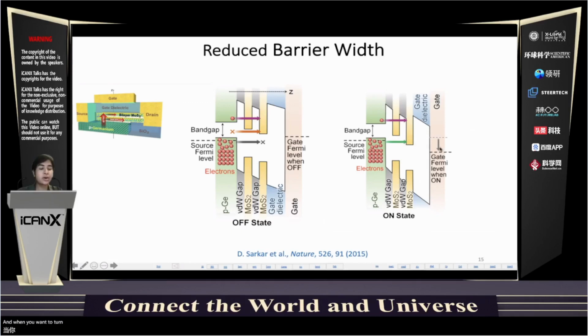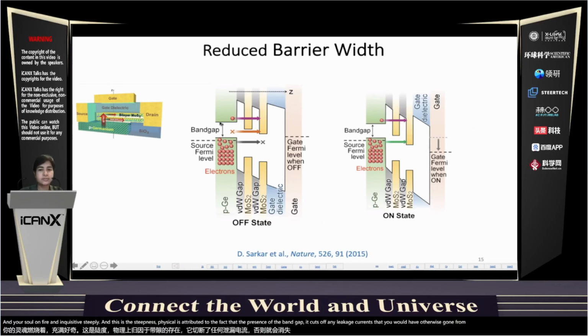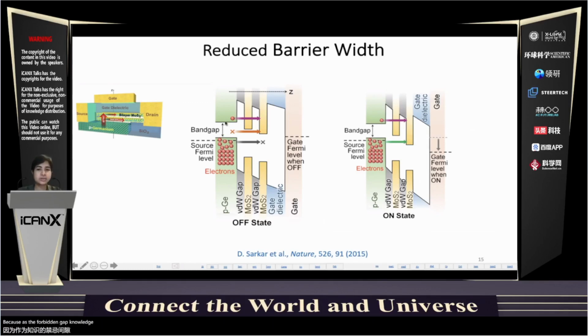And when you want to turn on the transistor, you apply a voltage to the gate, and you bring all the bands down. In that case, the filled regions in germanium actually coincide with the empty regions in molybdenum disulfide. So a lot of electrons can flow from the 3D source to the 2D channel, and so current increases steeply. This steepness is attributed to the fact that the presence of the band gap cuts off any leakage current that you would otherwise have got from this region, because it's the forbidden gap and no electrons are there. So we are basically cutting off the Fermi tail from here.